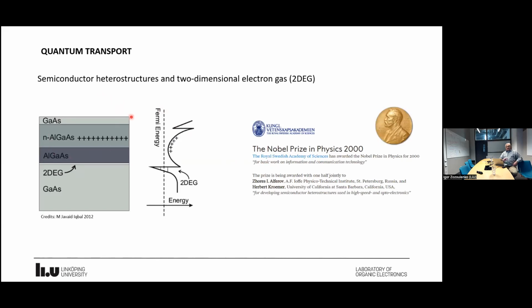you also have a semiconductor heterostructure. In this case, this is a layer of gallium arsenide, doped aluminum gallium arsenide, again aluminum gallium arsenide, and gallium arsenide. Basically, because of some electrostatics and the structure of this conduction band, at this surface you will create a state which is called a two-dimensional electron gas. This means that you will have this electron gas residing at this interface.